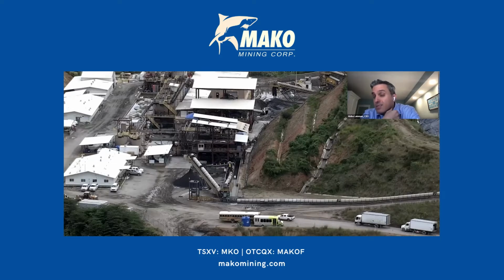Now, I'm happy to say that really since July, we've been getting our cyanide levels down to effectively zero. We were experiencing maybe 15 or 20 ppm of cyanide in the latter part of Q2, and now it's down to about 2, which really doesn't have any major effects. So our detox system is working. Our CIL is actually working as a CIL versus a CIP.